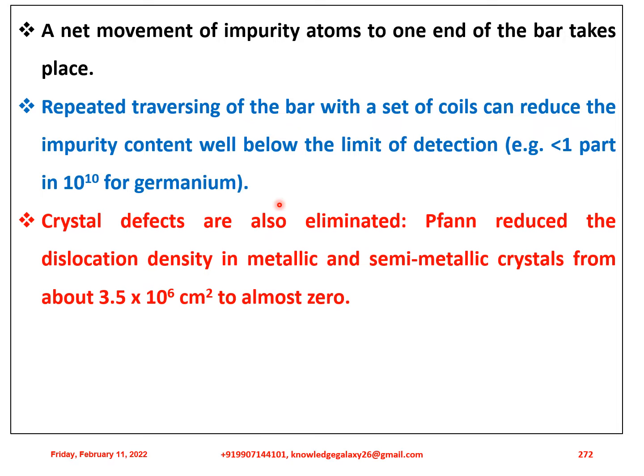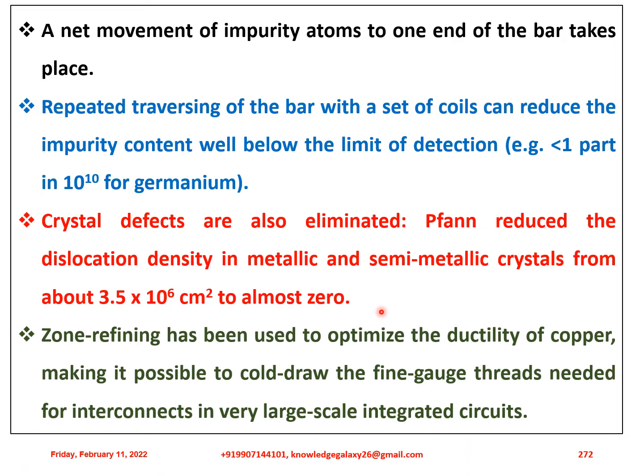Crystal defects are also eliminated, that is Pfann reduced the dislocation density in metallic and semi-metallic crystals from about 3.5 × 10^6 per square centimeter to almost zero. Zone refining has been used to optimize the ductility of copper, making it possible to cold draw the fine gauge threads needed for interconnects in very large scale integrated circuits.